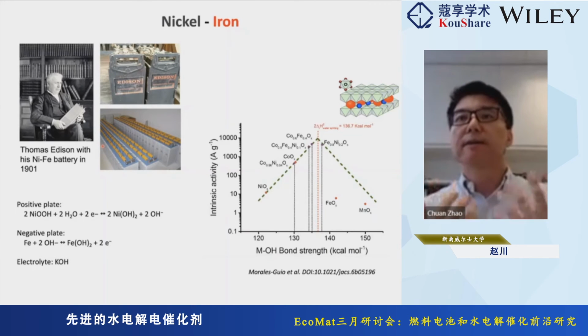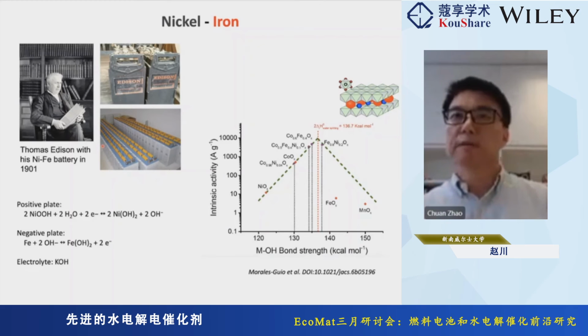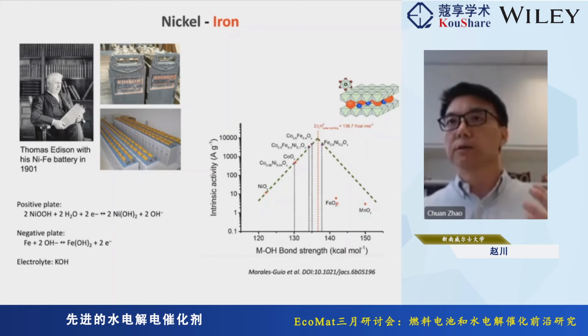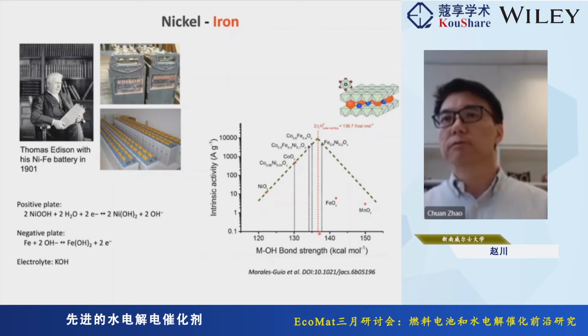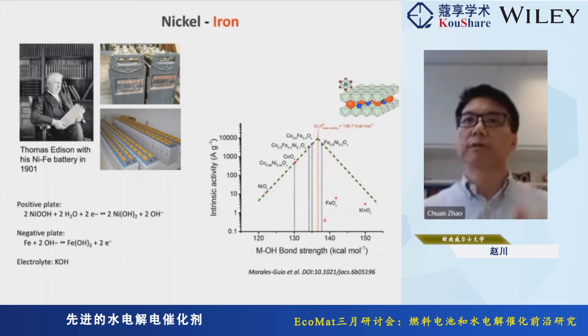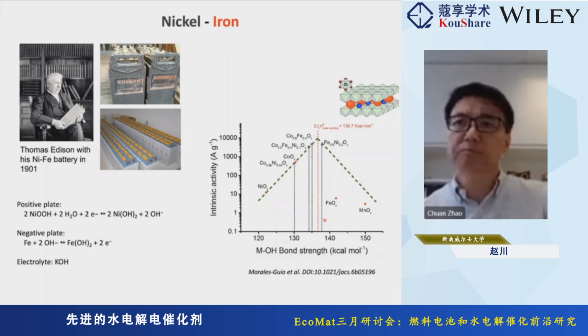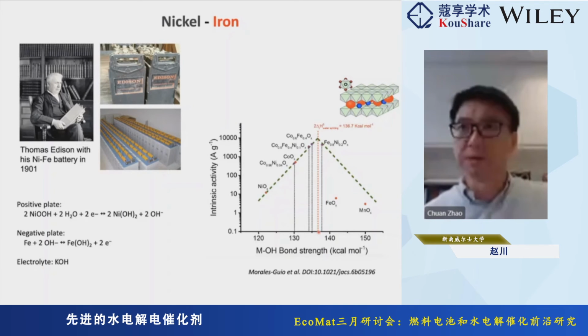We can understand this better now by, for example, using this volcano plot where we can see the intrinsic activity as a function of the metal OH bond strengths. Neither nickel nor iron alone is a good catalyst for OER. However, when they are combined together, they actually have an optimum bond strength for OH, not too strong, not too weak, which gives us the best OER performance.